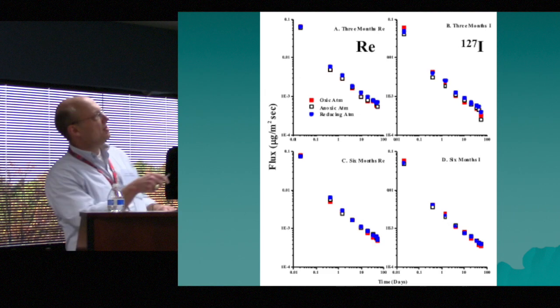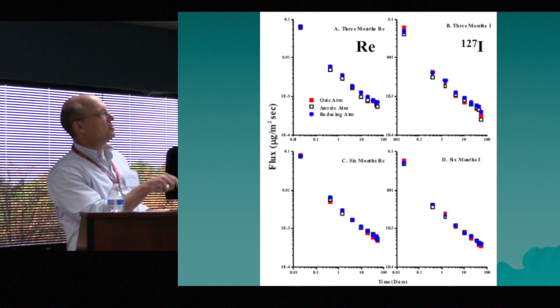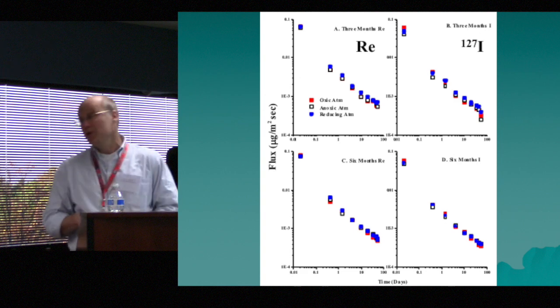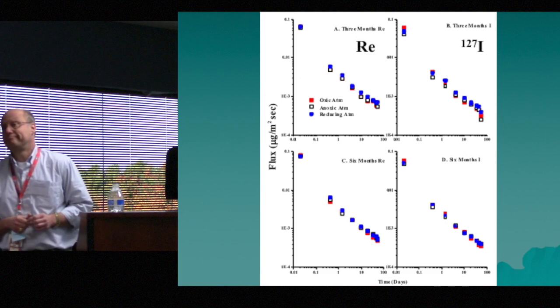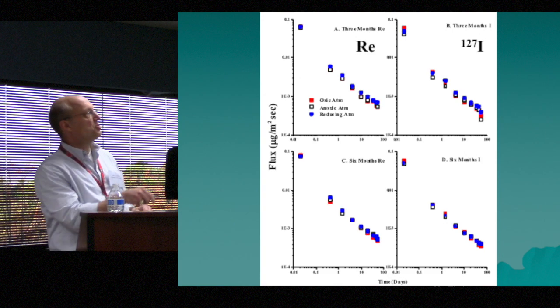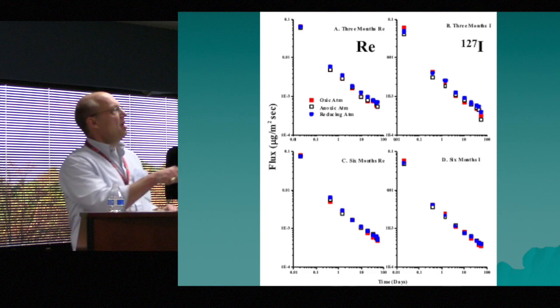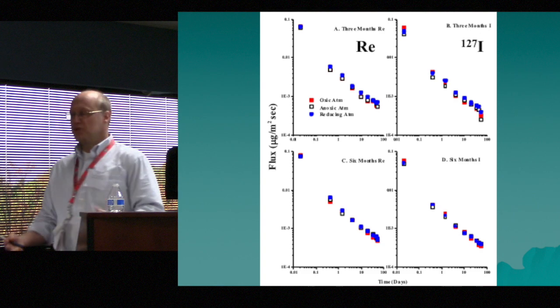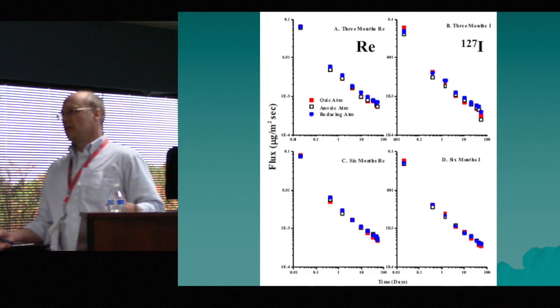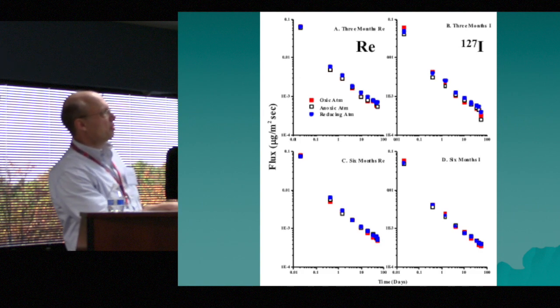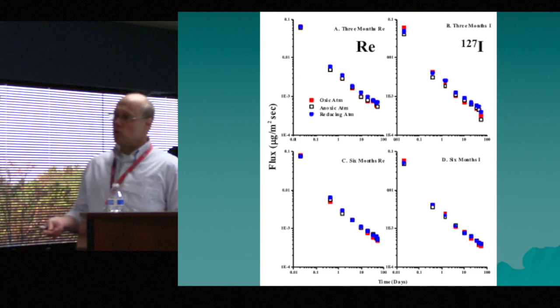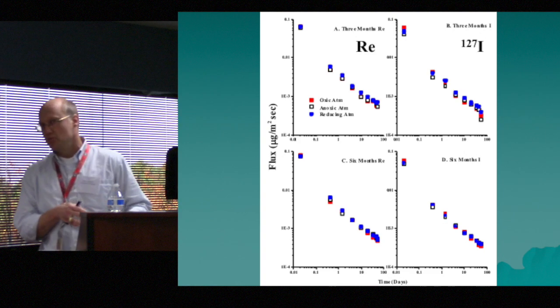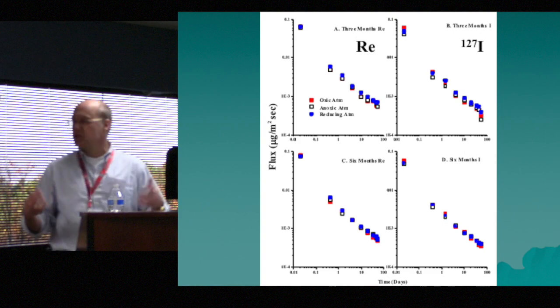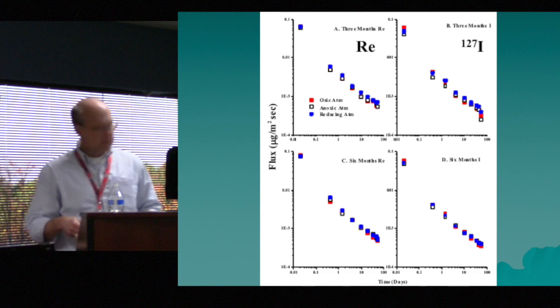The other thing is that these were the 3 different treatments, and what you see is that for both rhenium and iodine 127, you don't see any difference, really. Essentially, all of these lines are on top of each other, and also, if you try to rank them as to which one you think would be more immobilizing, it doesn't seem to follow the pattern that you would ever say. So you don't see that the reducing one is always the slower flux, while the oxidizing one is always the faster flux. It just looks like experimental noise. Next slide.